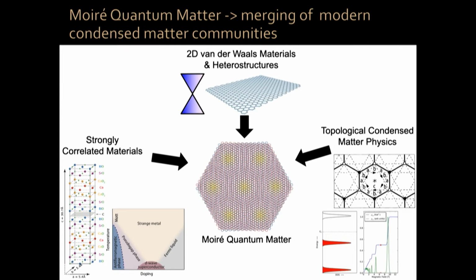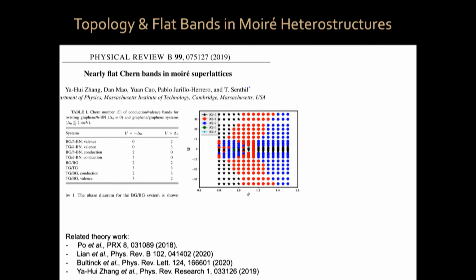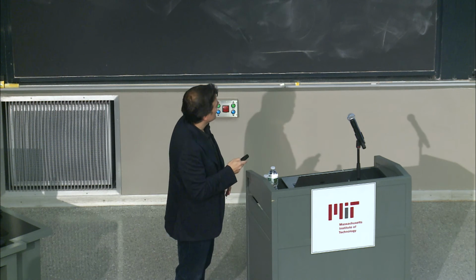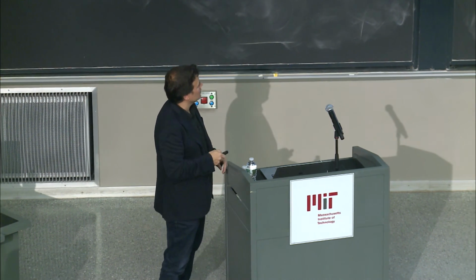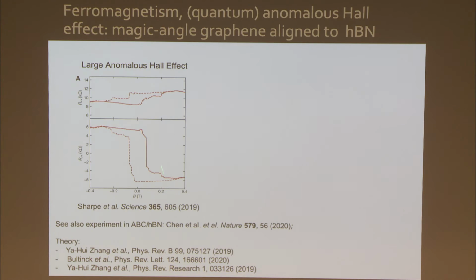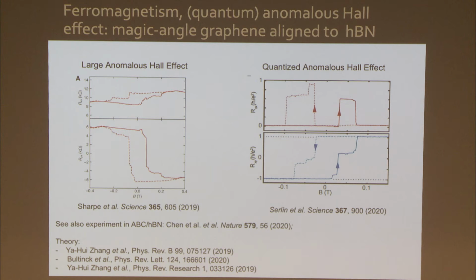Yeah? In fact, just a few months after our discovery, together with my theory colleague, Senthil, we proposed that there would be all of these topological physics, nearly flat Chern bands in various types of Moiré superlattices with different types of Chern numbers. And there was a lot of other theoretical work also at about the same time. And then just a few months later, the group of David Goldhaber-Gordon at Stanford University showed this very large anomalous Hall effect, okay, a finite Hall signal at zero magnetic field. And then 6 months later, the group of Andrea Young at UCSB showed the actual quantized anomalous Hall effect, quantum Hall effect at zero magnetic field in these systems.